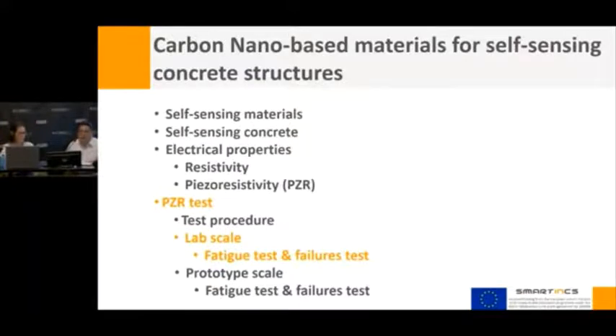A preliminary verification of the electrical properties of the functionalized material was carried out. The property varied in relation to the amount of functionalized addition with respect to a sample with a carbon-based addition. It was observed that the resistance of the sample with the addition decreased by an order of magnitude. With these samples, we worked with the variables that we saw previously to obtain the test protocol both to fatigue and to failure, the two kinds of tests.